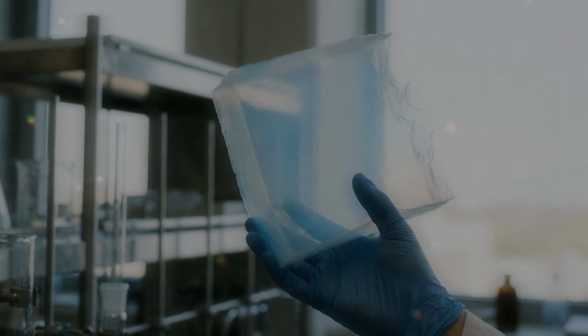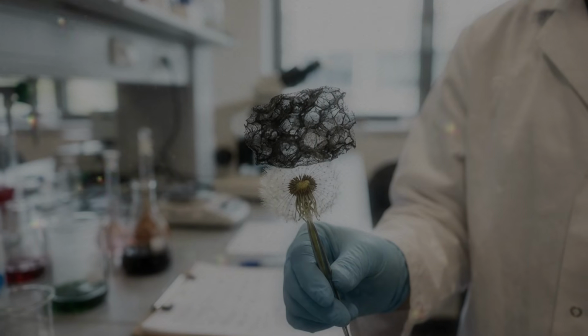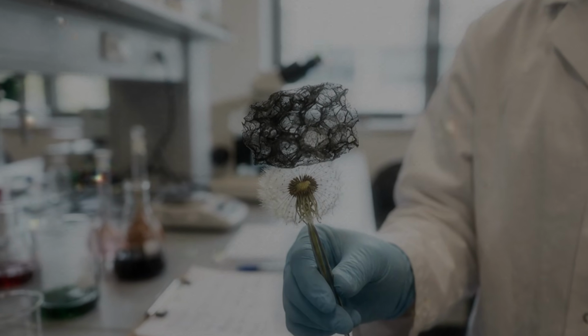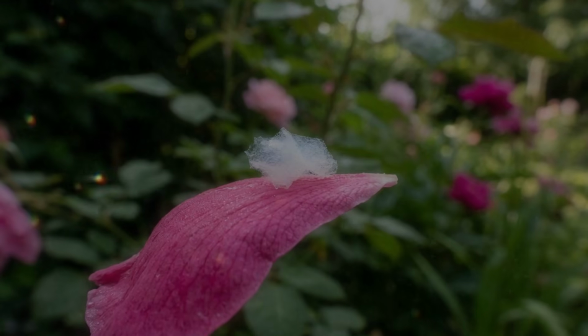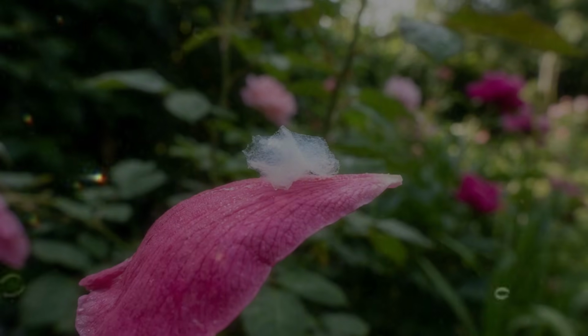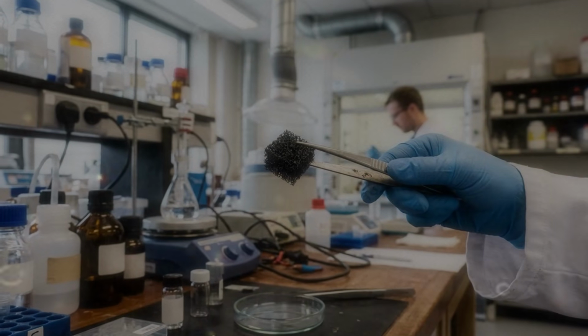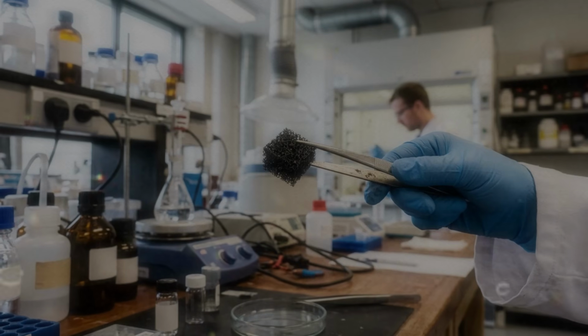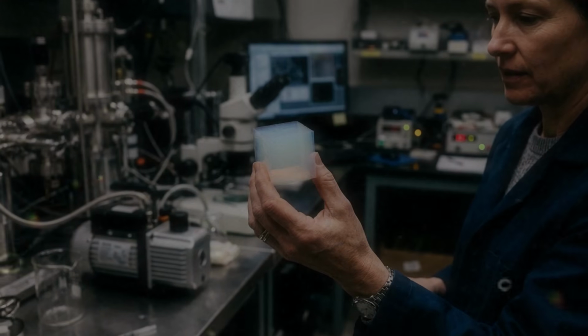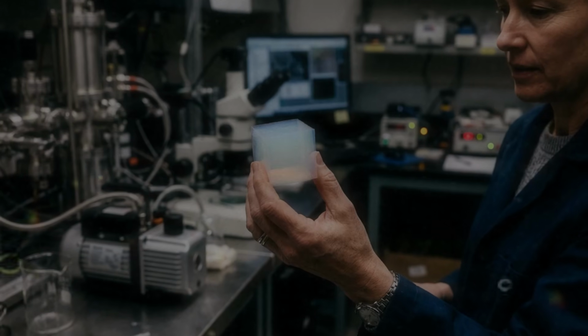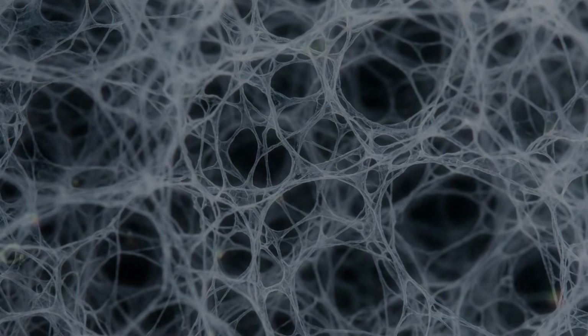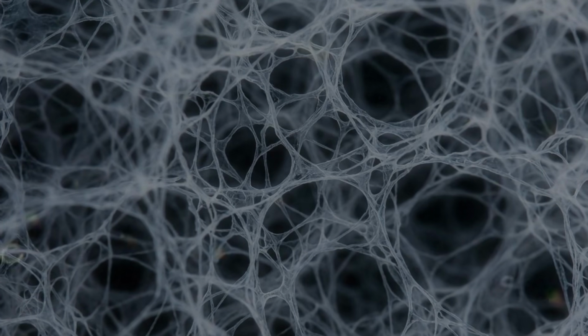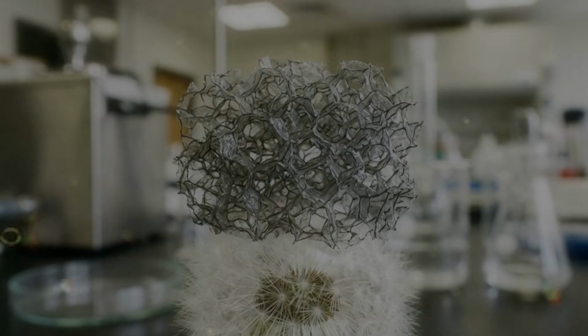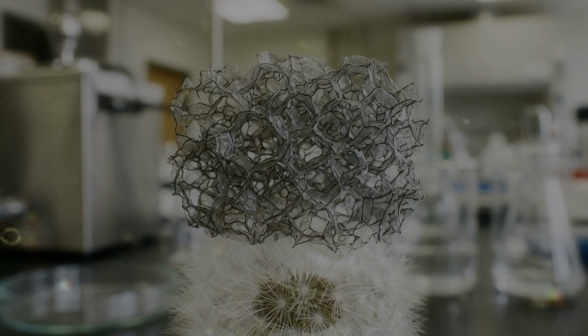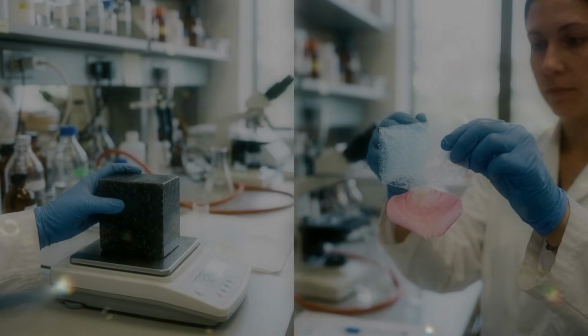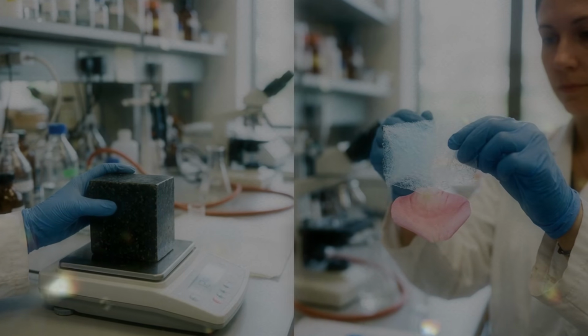When pressure is applied, the sheets may bend before the carbon bonds themselves are seriously stretched. This is useful because bending can absorb force without immediate breakage. The walls of the pores buckle inward, the open spaces become smaller, and neighbouring sheets move closer together. If the network has enough flexibility, it can recover when the pressure is removed. This recovery is one reason some graphene aerogels behave like very light sponges. They can be compressed to a fraction of their original size and then expand again. The process is not always perfect. Repeated compression can leave permanent changes. Weak contacts can separate, sheets can become stuck together, small cracks can grow. Still, a well-designed structure can survive many cycles.